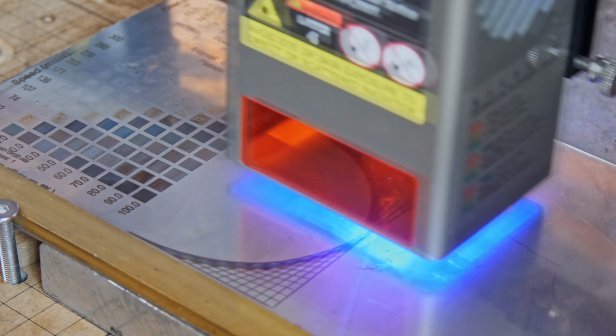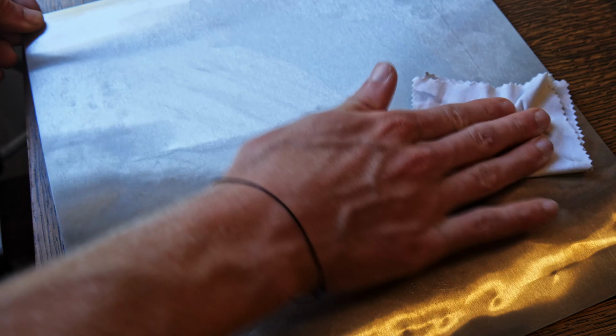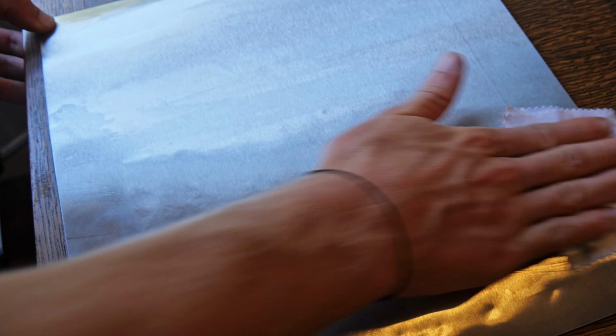It took two little test pieces for me to check that the laser settings were actually in the right order and that the gradient was looking nice. It's important to thoroughly degrease and clean the surface of the steel before engraving, because that'll affect how it reacts with the oxygen and the resulting colour produced. It's very easy to get handprints and dirty fingerprints that will be lasered into the final design, and it looks